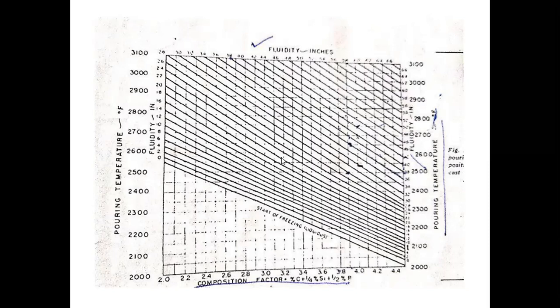In automobile casting, big castings will have larger sizes, but the quantity will be less. For mass production, ductile casting will have some other calculations for risering. Risering is the most important thing in the case of ductile iron. For cast iron, because wall thickness will be less, it is important to calculate the pouring time and temperature so that defects are not there.